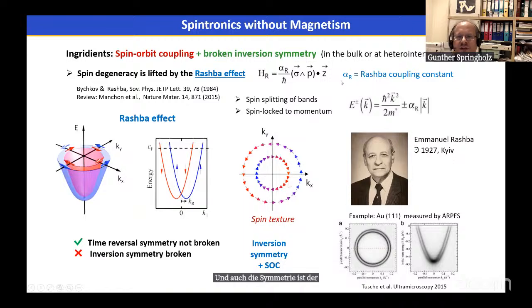These symmetry breaking mechanisms can be completely different. In the case of ferroelectrics, it's the displacement of the sublattice atoms. In the case of zinc blende semiconductors, you have a crystalline inversion asymmetry, because the crystal structure itself is not inversion symmetric. And then you have thin film heterostructures, where at each interface you have an asymmetry of the band structure, because when the band structure from one material evolves into the band structure of another material, you always have gradients in the band edges,